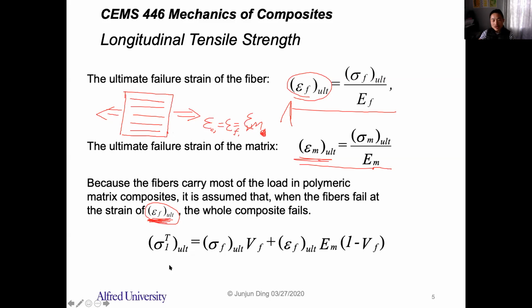Okay, so based on the rule of mixture, we know that the ultimate strength of the composite can be calculated by the stress applied to the fiber and the stress applied to the matrix, right? So we know the composite in the unidirectional direction will equal the stress on the fiber times the volume fraction of the fiber plus the stress of the matrix times the volume fraction of the matrix, right? So this is the rule of mixture. And for the ultimate strength, we have this as the ultimate strength of the composite, right?